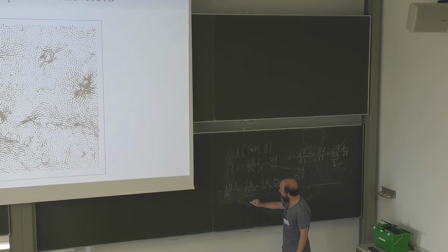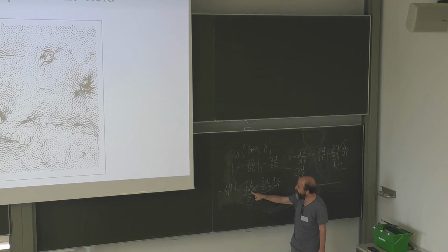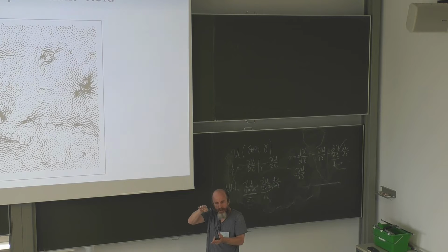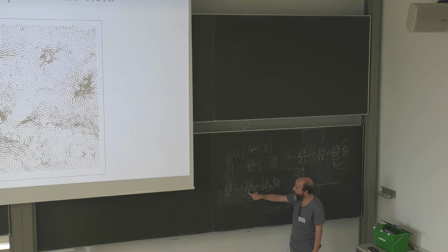Now, this is the Hessian matrix. It's a matrix of second derivatives. This other term is something I call psi_i. This is the variation of the force during an affine strain. It means that if you shear your system finely in the linear response, there is a force residue. This is the change of the force caused by the affine response. When you shear, you do not guarantee that the forces remain zero. That's the whole point.